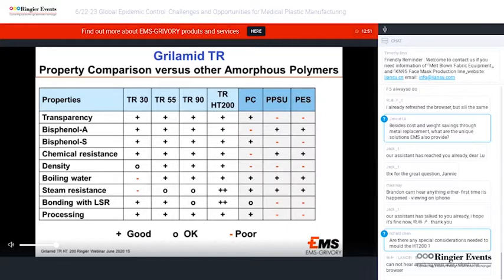On this slide, we compare three main Grilamid TR grades with PC, polyphenylsulfone, and polyether sulfone. The judging here is that a red is negative or poor, a hollow black circle is okay, and the plus symbol is good. For the transparency, they all show a good transparency apart from the sulfones, polyphenylsulfone and polyether sulfone. Their transparency is affected by their dark yellow brownish color.